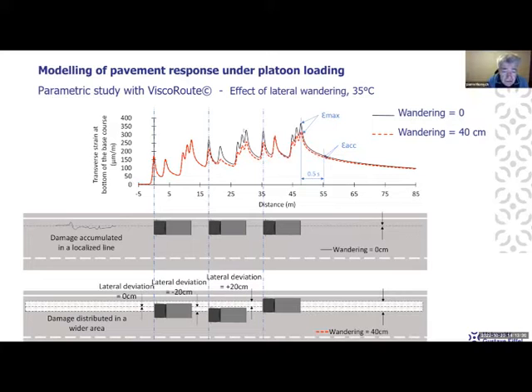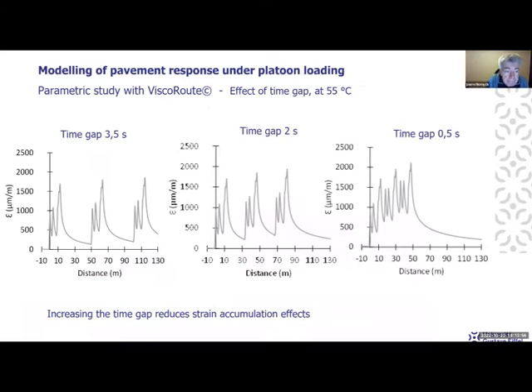And you can see the effect. The black curve corresponds to the tracks with no wandering. So you have a high strain accumulation after the passage of the second and third track. And when you increase the wandering, you reduce considerably the strains under the second and third track. And so you reduce the maximum strain level to which the pavement is submitted by spreading the loads laterally.